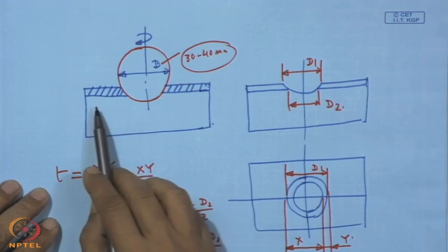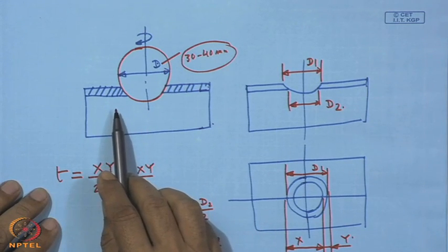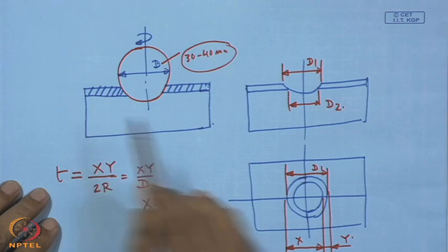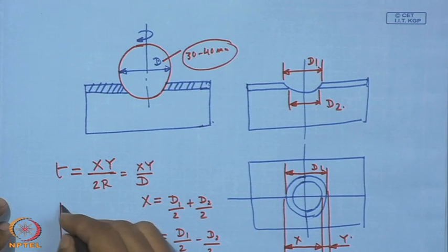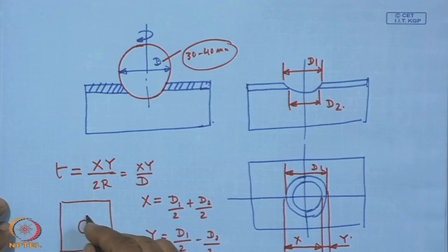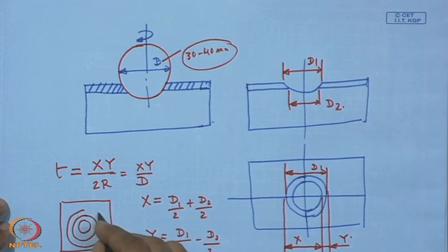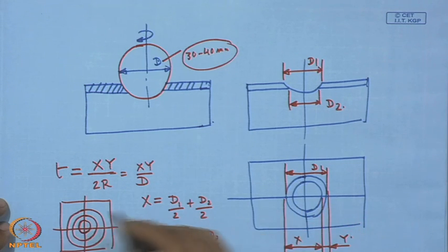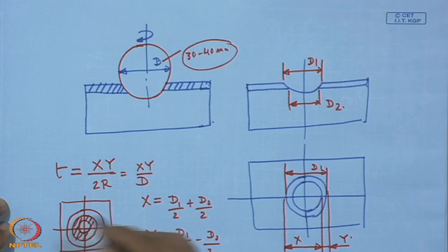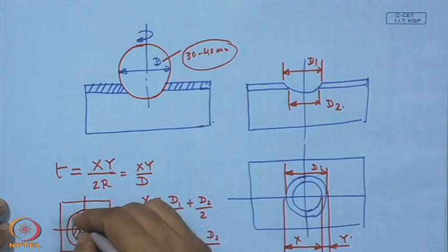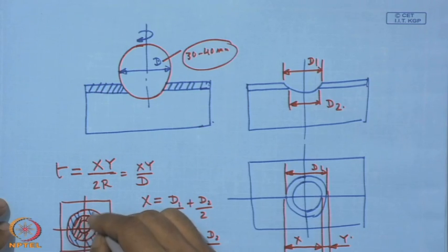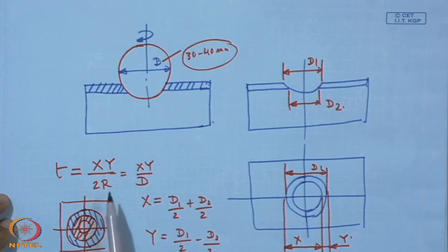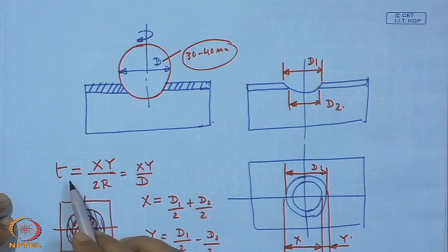Now, instead of a monolayer coating, if we have a two-layer multilayer coating, in that case it is also possible to have three circles instead of two circles. So, in the central zone the coating is exposed, and we have one coating here, and we have another coating in the outermost ring. From there, by having the respective values of x and y, we can determine the values of T1 and T2 for these two rings.